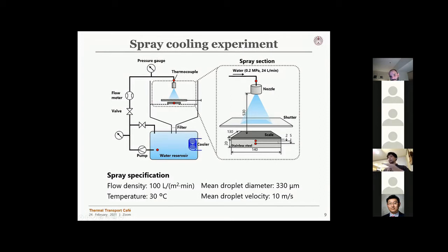We have thermocouples embedded here so that we can calculate the surface temperature, not really the surface temperature - we obtain the temperature at the interface between this oxide layer and the stainless steel plate, just by solving the inverse problem of heat transfer, heat conduction.